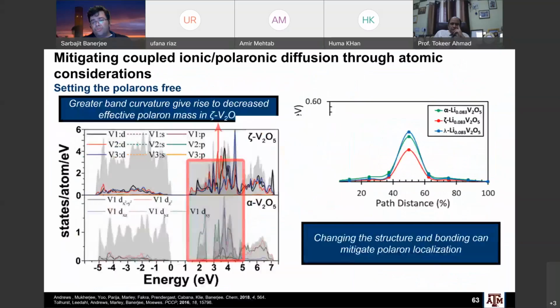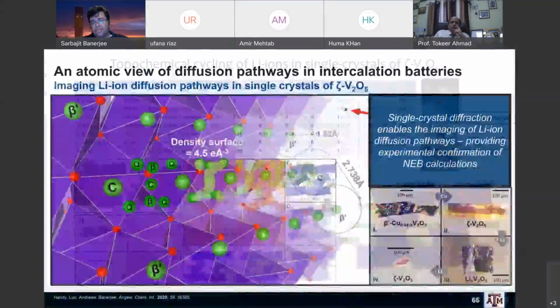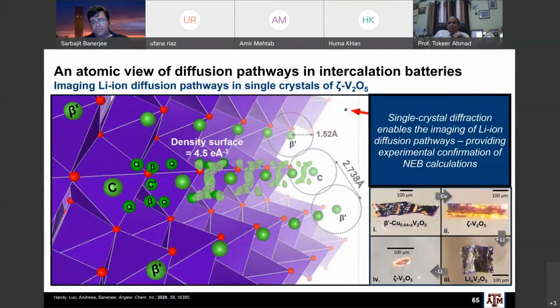But what we've been recently able to do is to take these single crystals, for instance, of Zeta V2O5, lithiate them, and then take the lithium out, and we can measure, using powerful single crystal diffraction, the electron density inside the single crystals as they are getting lithiated. This allows us to really see. It's very different from making lithium V2O5 from direct synthesis, where everything settles into its thermodynamic site.